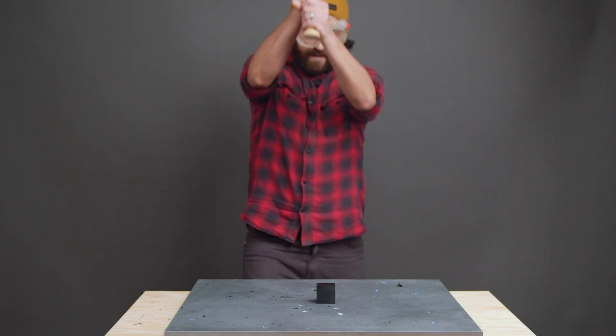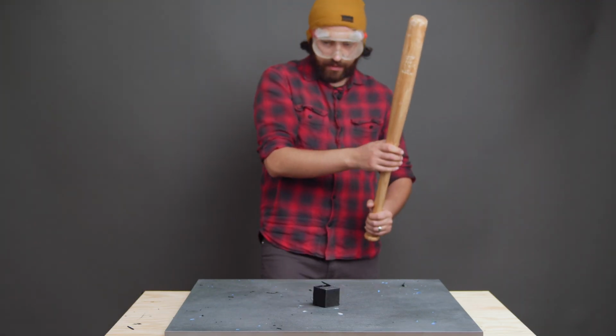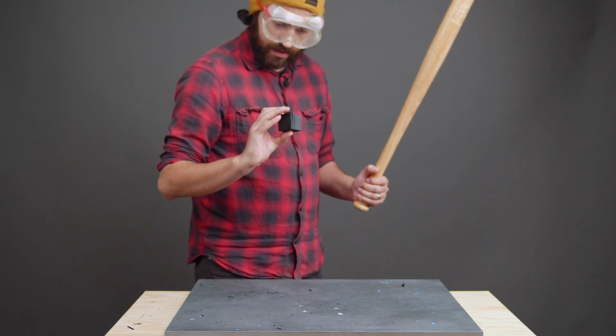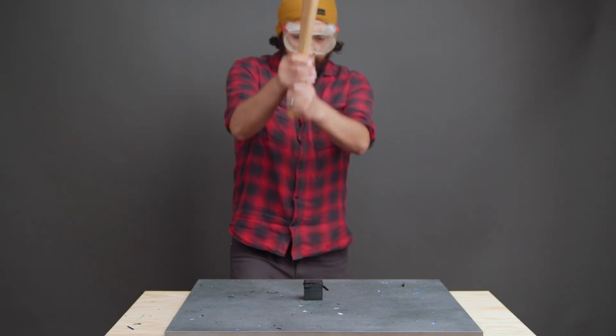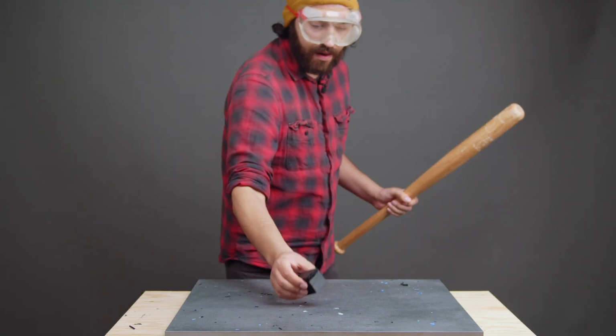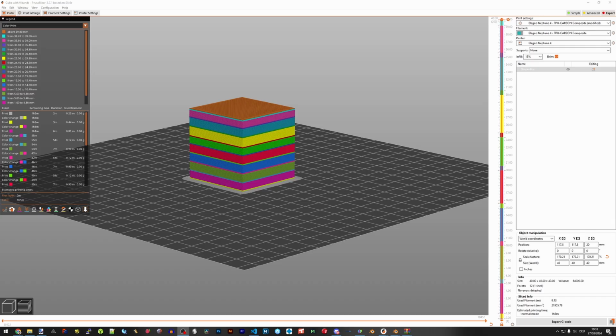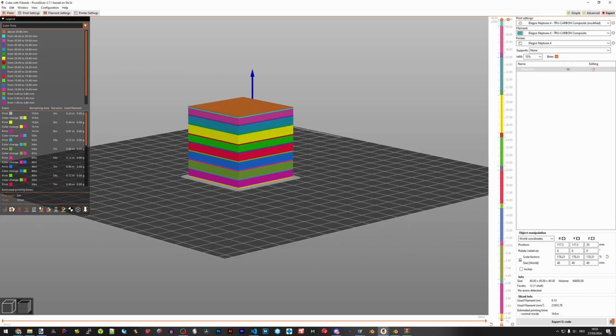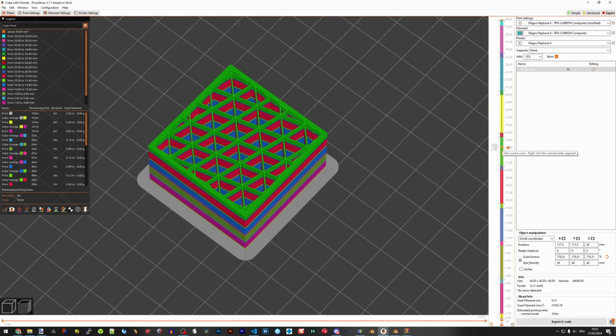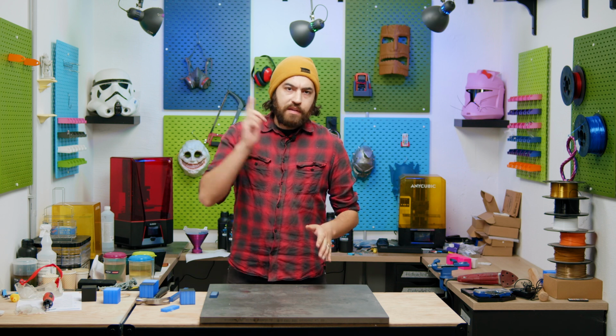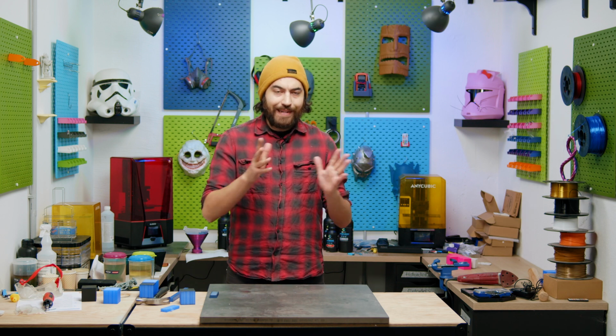But the one that did the best, surprisingly, is the one with just 4 top and bottom layers of solid infill, and the rest is 15% triangular infill, and the TPU is spread evenly throughout the cube. So it doesn't have any thick TPU on the top or the bottom. It's just spread throughout, which is interesting. That did really well.